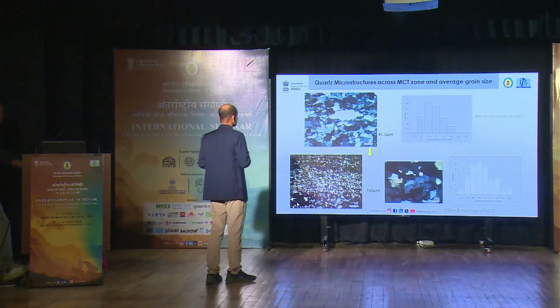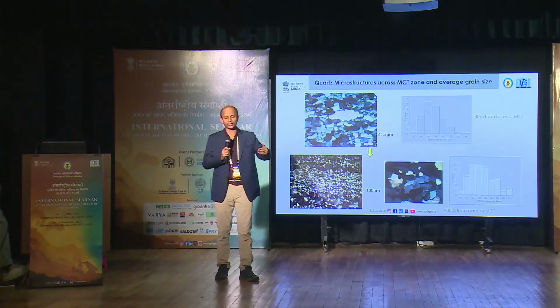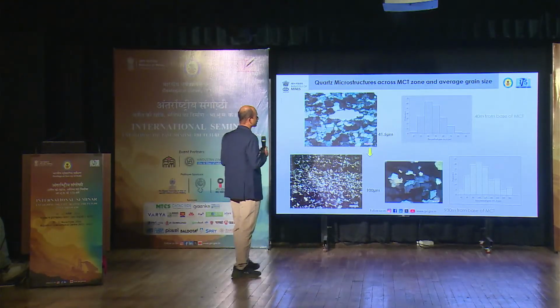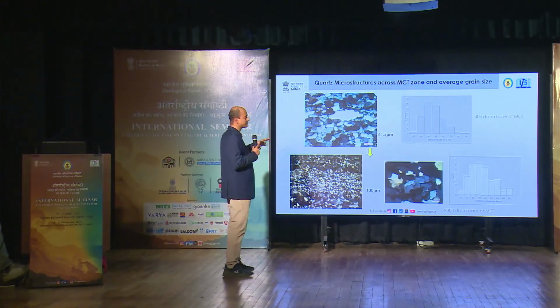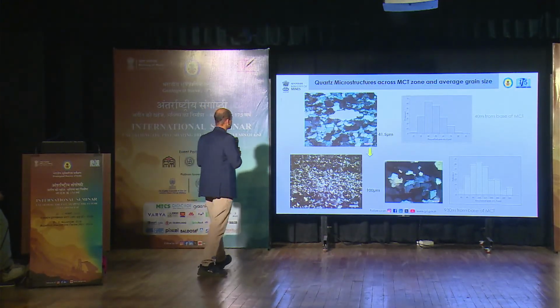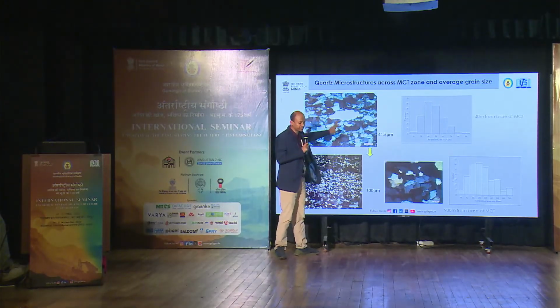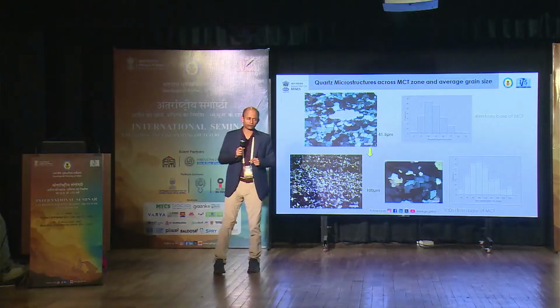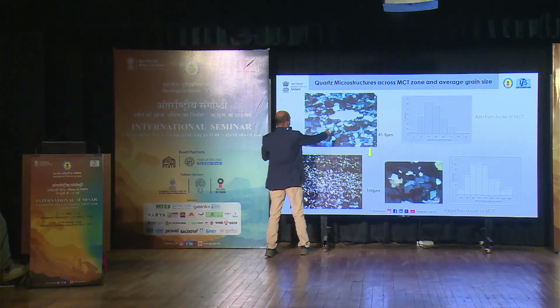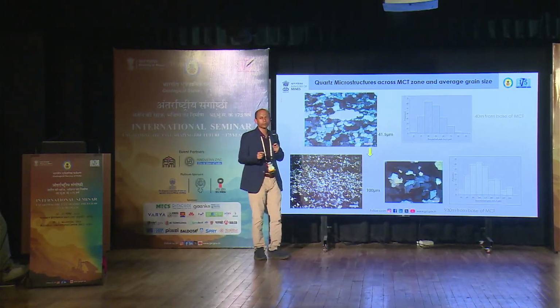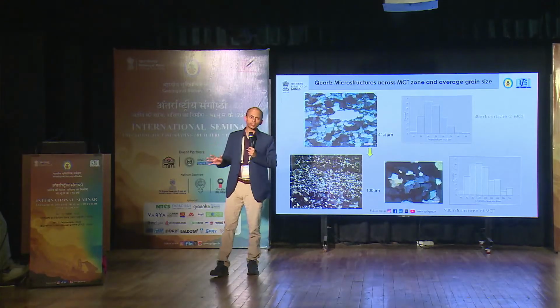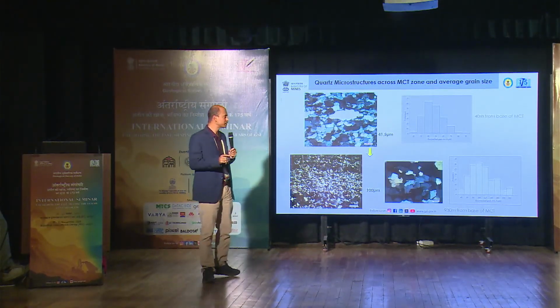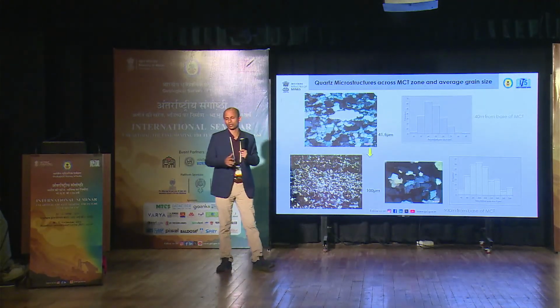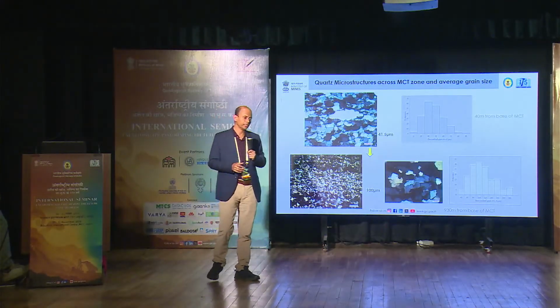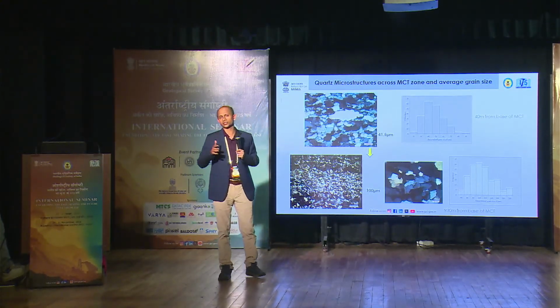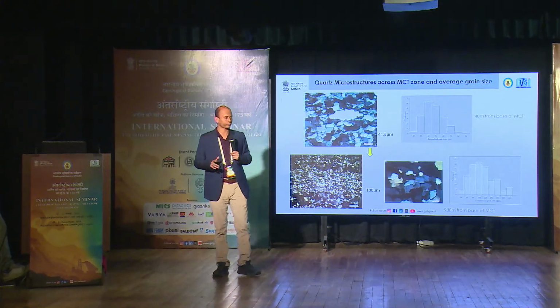Next. So as I have already mentioned, we have collected samples right across the MCT zone. The first sample was collected 40 meters from the base of the MCT. What we observe here is the average grain size is 41.5 micron. Here we can see these are the typical core-mantle structures. These are typical of subgrain rotation deformation. If you look closely, there are a few evidences of new recrystallized grains being formed by bulging recrystallization. So here we have observed dominantly subgrain rotation with occasional occurrences of bulging recrystallization, and also the experiments by Stipp et al. in 2006 and later in 2010 have shown that the bulging recrystallization to subgrain rotation transition lies at around 40 micron for quartz.